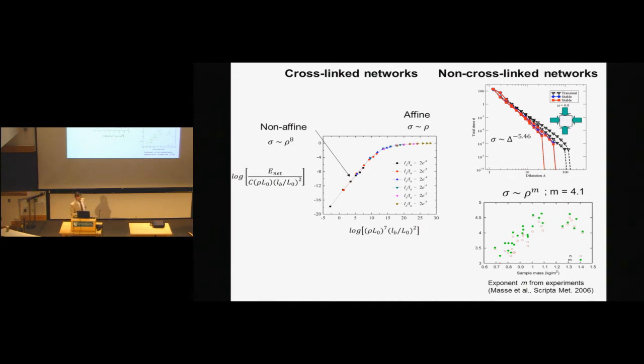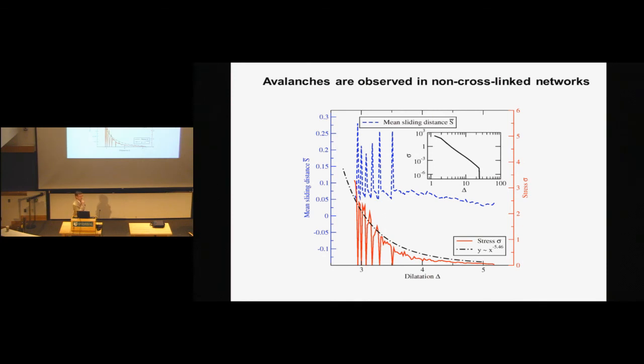Okay? And the last thing I want to show you, just to underline how complex this type of system may be, is this. So you start compressing this non-bonded network. And you look at, let's say, stress versus strain, or you look at the stability of the deformation in fact. Right? At the beginning, that is when the fibers just start coming into contact, everything is smooth. So I'm looking at stress, and you see stress versus strain is a relatively smooth curve, this range over here. Right? So I'm just trying to compress this thing. But when the density gets large enough, there is a threshold beyond which stress versus strain becomes this jagged curve.